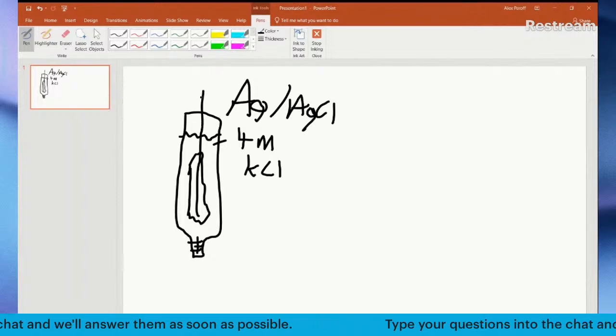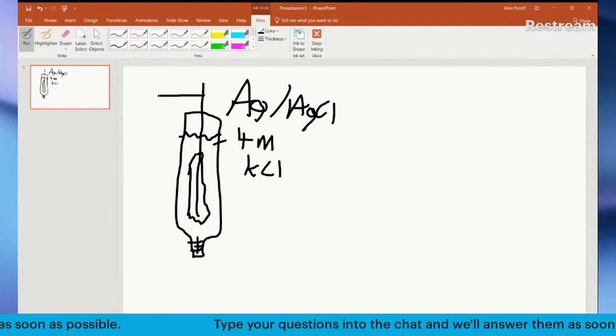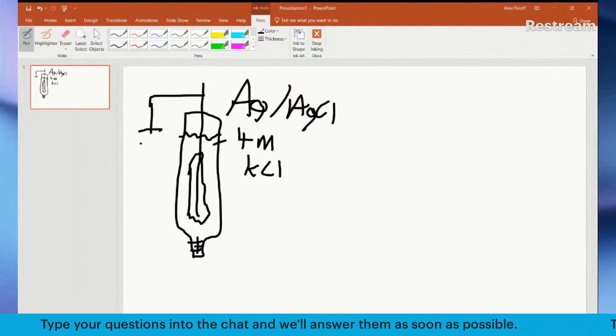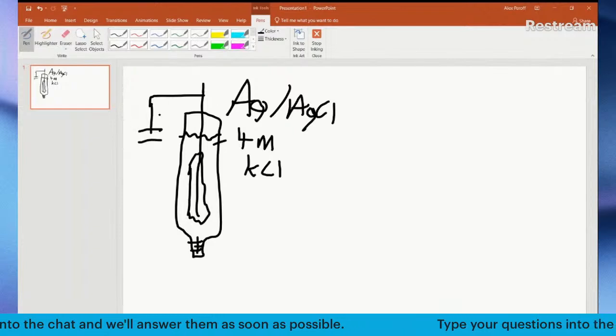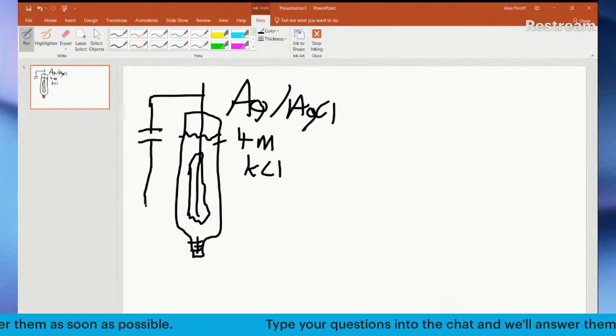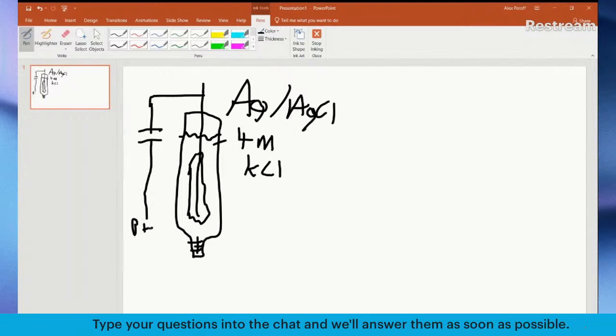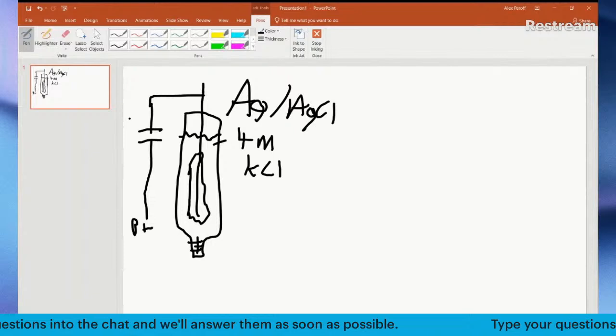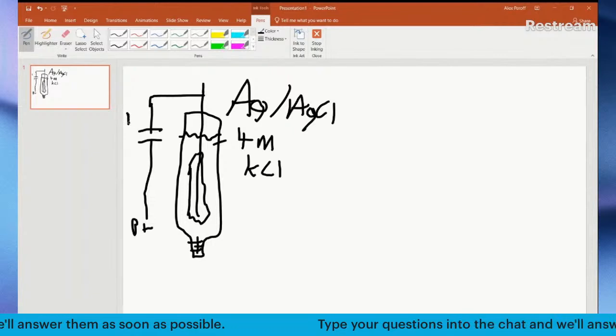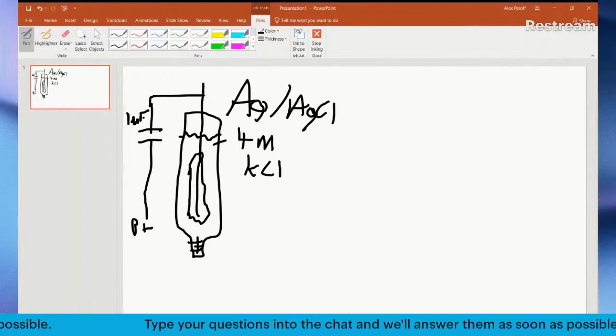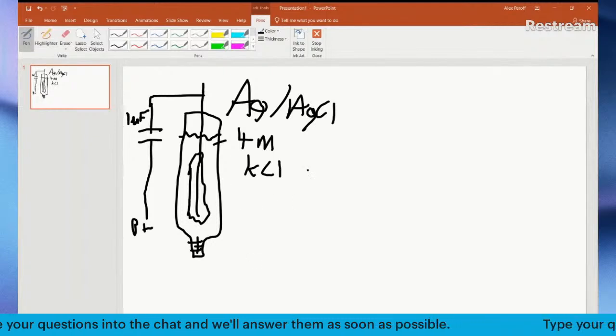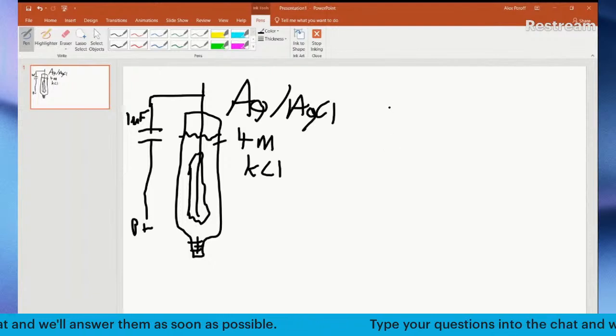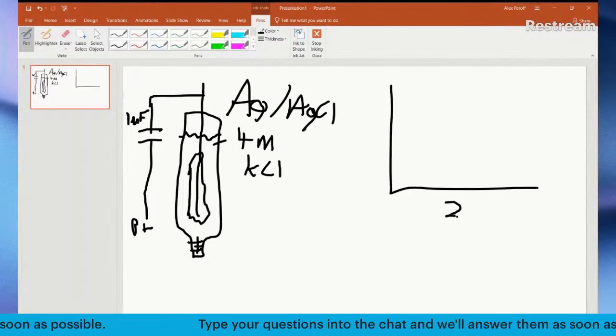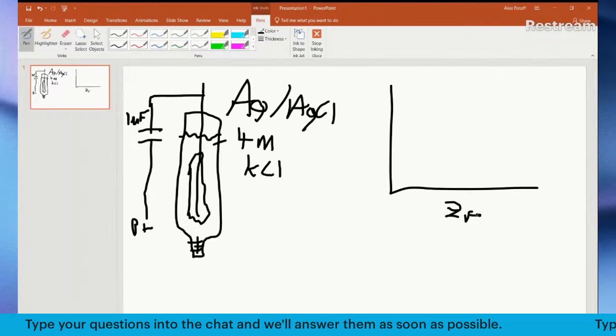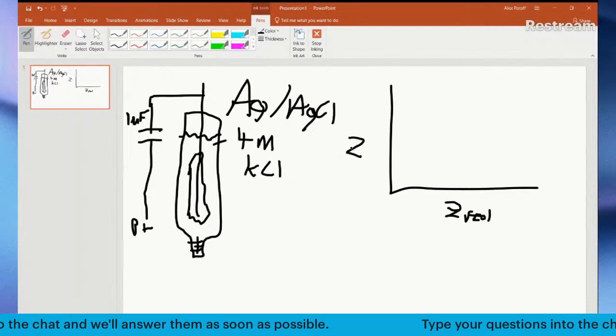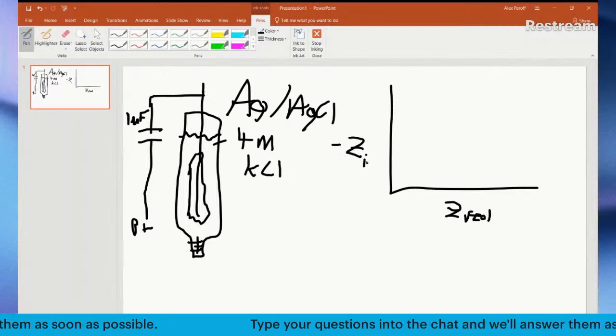Now, a reference electrode shunt is when you have another electrode in parallel with this silver chloride, but it's connected to a capacitor followed by, say, a platinum wire. So it's a conductive platinum wire, and this capacitor, let's just say, has like 1 microfarad of capacitance. And so there are these things that happen in EIS where when you have, say, your Z real, and then you have your negative Z imaginary.